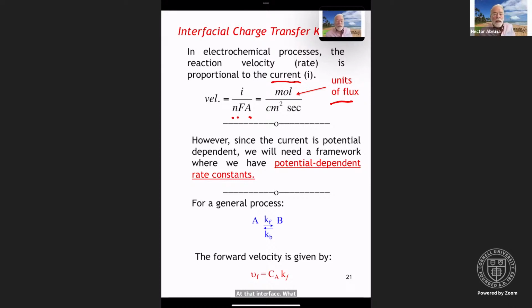What is different here is that the current will be potential dependent. And because of that, we need a framework that takes into account potential dependent rate constants. While in homogeneous solution we have temperature dependent rate constants, here we have the added variable, a potential dependent rate constant, because by the potential, we control with great finesse the driving force of the specific electrochemical processes. We can start with the most generic process. A in equilibrium with B, we have k forward and k back. The forward velocity can be defined as the concentration of A times kf.